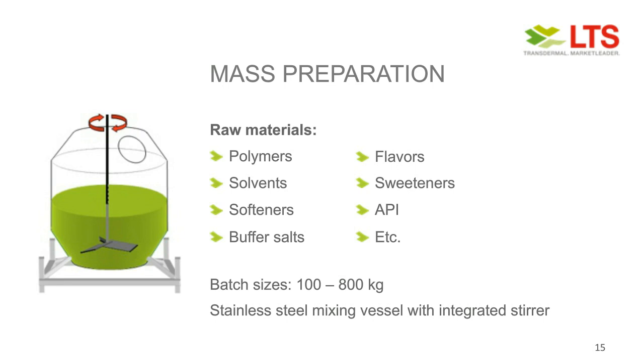But very often this easy approach is not applicable, since we're talking about dispersions or homogeneously distributed emulsions, where we have to stabilize the emulsion, the two-phase system within the mass preparation process. So this could be as easy as here, but most likely it's a bit more complicated. But at the end, we're ending up with a polymer mass in a transfer vessel, which is then brought to the next step, to the coating step.